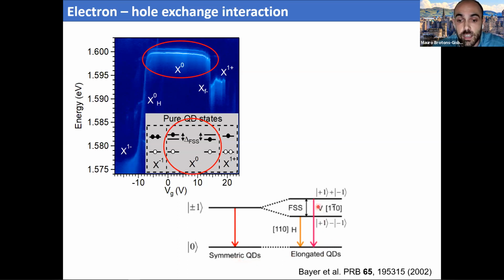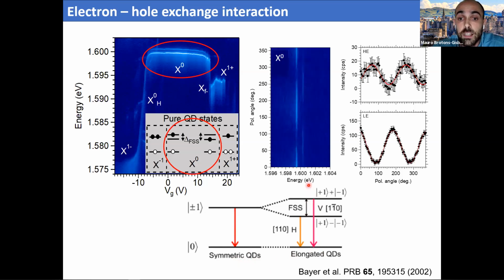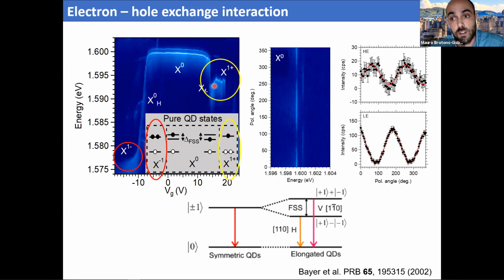And this gives rise to two linearly polarized emission lines that are cross polarized, as you can see here, okay? Interestingly, if we look at the negative and positive trions, we see that we only have one emission line, so there's no fine structure splitting. This can be understood by the fact that when you have a second electron or a second hole in the dot, you're removing the electron-hole exchange interaction, and therefore there's no fine structure splitting, okay?